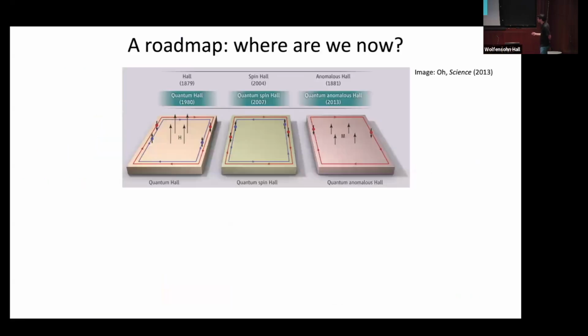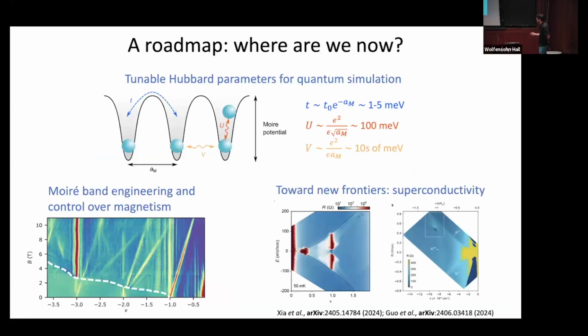So just for those who aren't aware, let me go to some backup slides. This is two very recent arXiv preprints that show that in twisted tungsten diselenide, in a certain narrow window of phase space as a function of electric field and filling factor, actually in two very different regimes, by the way, there's been superconductivity which was observed. This is tremendously exciting. I think it puts twisted transition metal dichalcogenides on similar footing to graphene in both systems, both graphene-based systems and transition metal dichalcogenide systems. You can get fractional Chern insulators, you can get superconductivity, and this is exciting for a whole host of reasons.